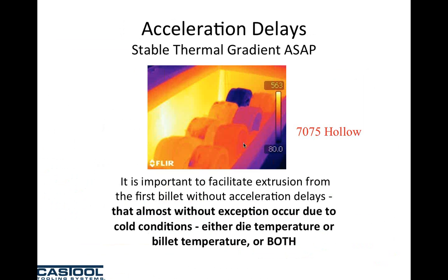Last week, again, I did 7 presentations to 7 extruders. We had maybe 25 to 50 people on each presentation, and just about every extruder was using 2 to 4 billets to start every die. The only reason you use startup billets is because your dies are cold. And if you're using startup billets to heat your die, one, it's very expensive. Just think, you could be using those billets to make saleable profiles instead of heating your die.